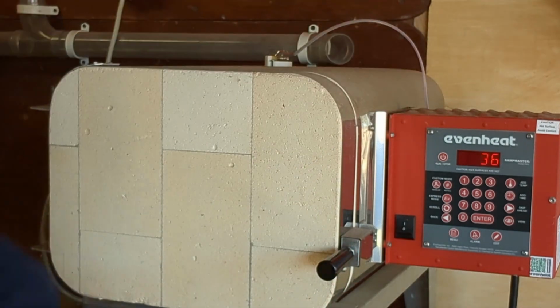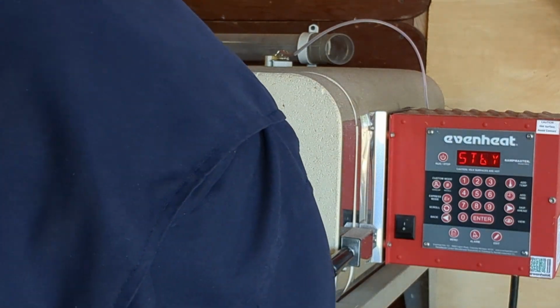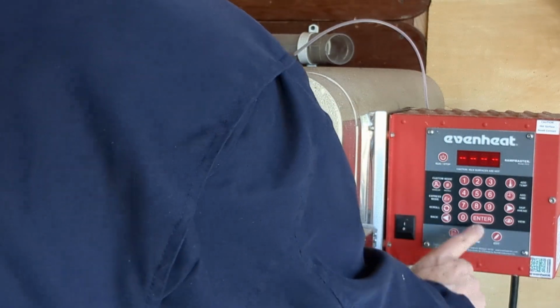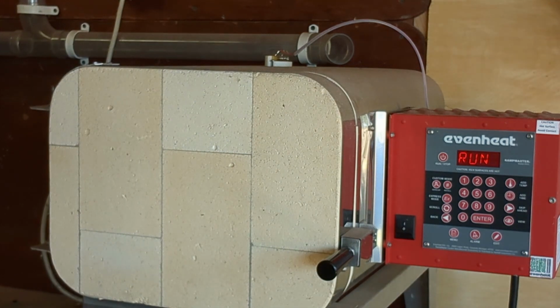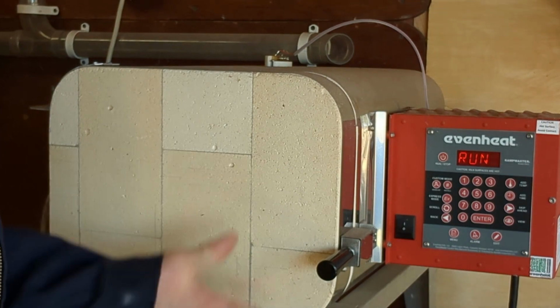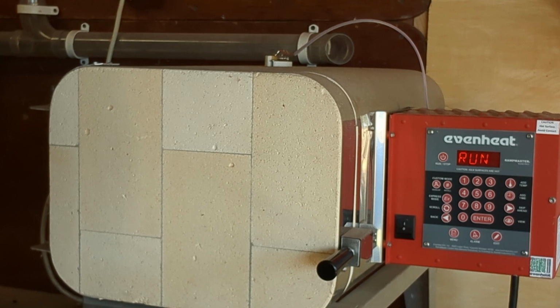I have the controls set and we're going to start this program. And it'll start heating up the temperature. You can hear the clicking. That's it turning the elements on and off. Since this is 01 tool steel, I have it programmed to go up to 1200 degrees and then hold that for 20 minutes. Then from that point to go up to 1475 and hold that for 30 minutes.